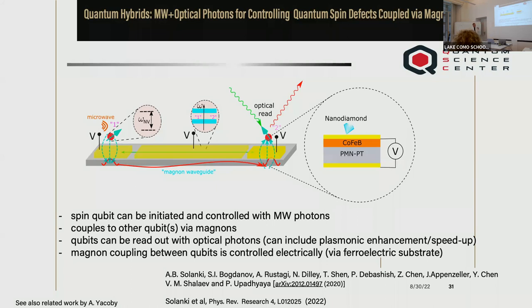And these qubits would couple with each other via magnons, because it's very important to couple, to entangle them, to take advantage of this broader information space. You need to create this entangled spooky state. So for that, magnons could be a very important way. And moreover, you read these spin qubits optically, through optically detected magnetic resonance. And you could also speed up this reading by using plasmonics. And remarkably, you actually could control the magnon coupling through a ferroelectric effect.